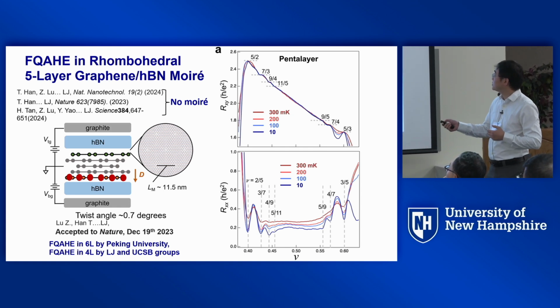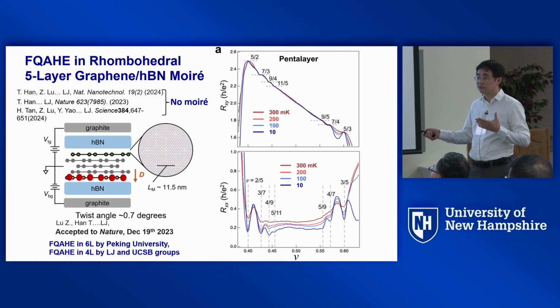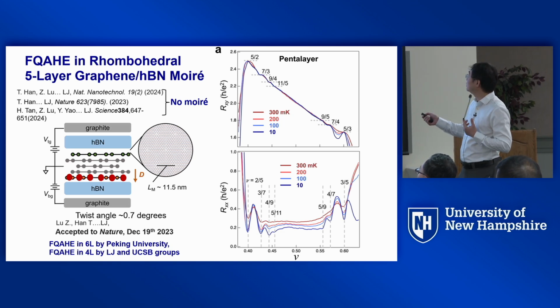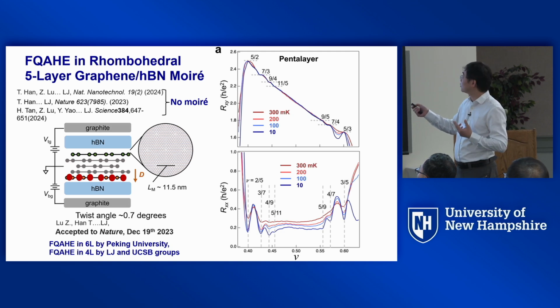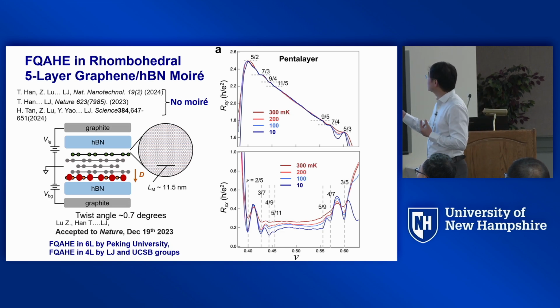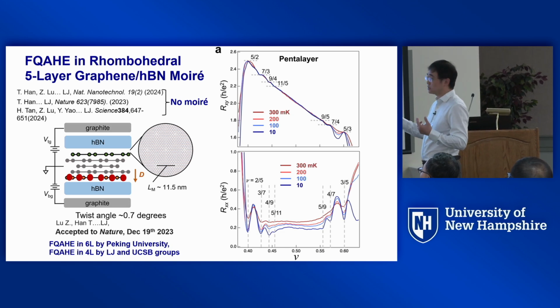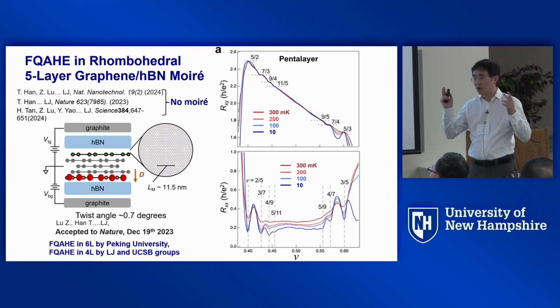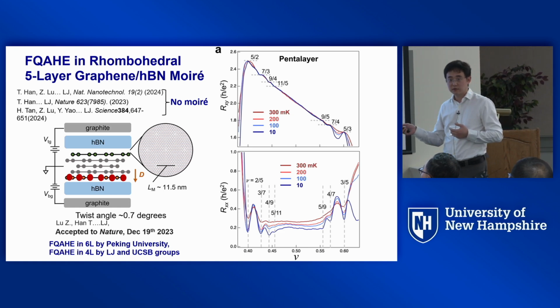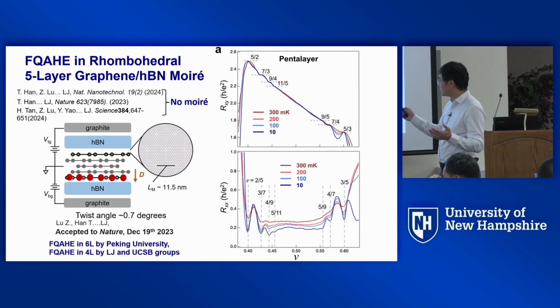In our case, we observed so far a total of 8 fractions. I'm showing 7 of them now. You see, these all follow the so-called Jain sequence. At zero magnetic field, you get plateaus in Rxy, and you get dips in Rxx. And this is robust, persisting to an electron temperature, not exactly 10 millikelvin, but probably 20, 30 millikelvin. Okay? So moire is indeed very powerful.